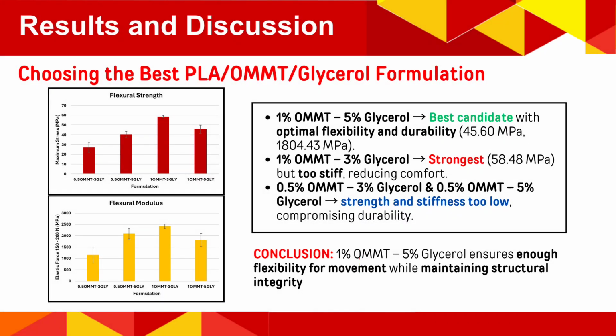Considering both tensile and flexural properties, the 1% nanoclay and 5% glycerol was identified as the best formulation. While the 1% nanoclay and 3% glycerol had higher mechanical strength, its increased stiffness could lead to discomfort. On the other hand, the 0.5% nanoclay formulations had lower strength, which may compromise durability. The 1% nanoclay and 5% glycerol provided the optimal balance of strength and flexibility, making it ideal for wrist splint